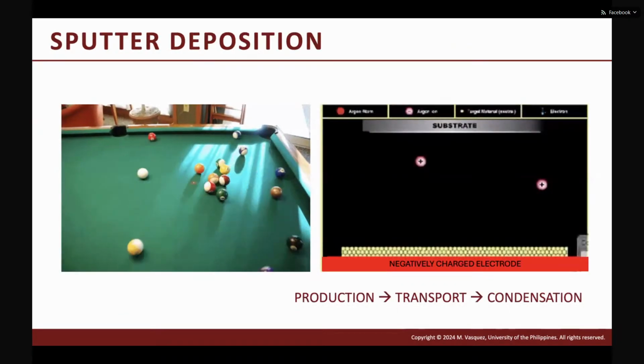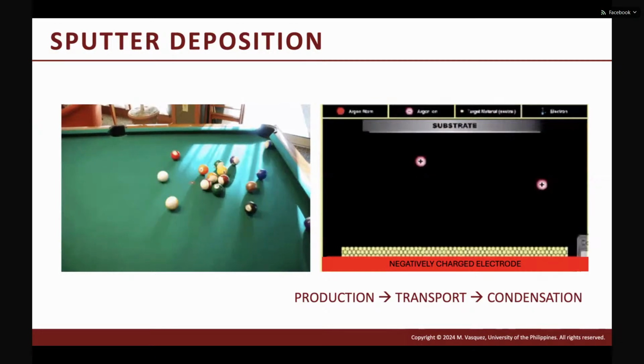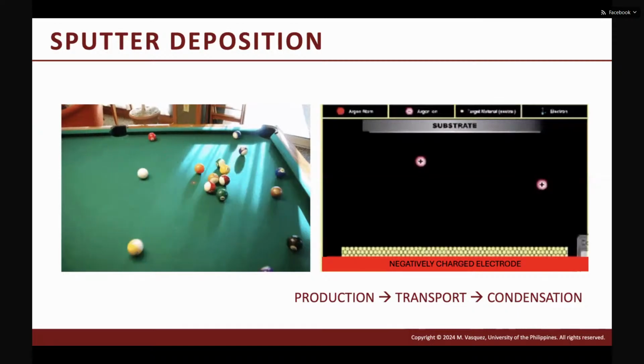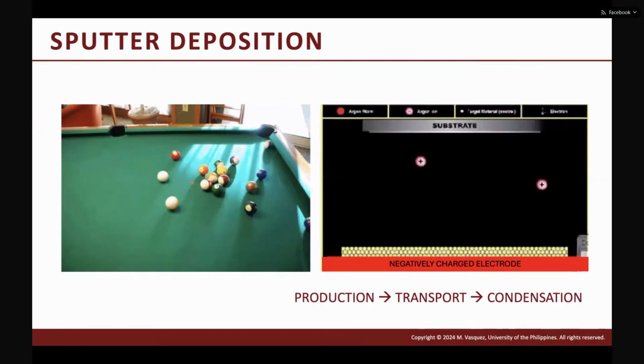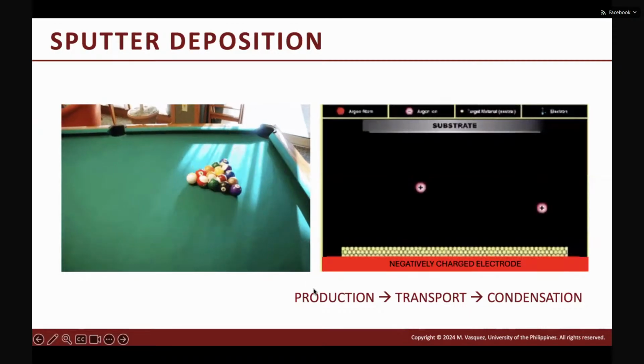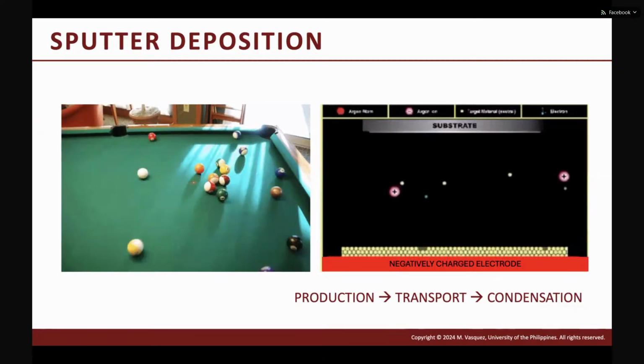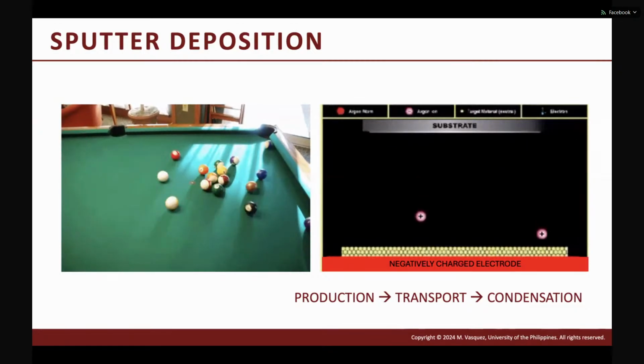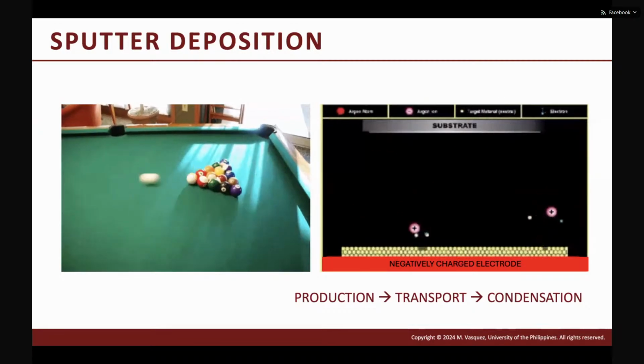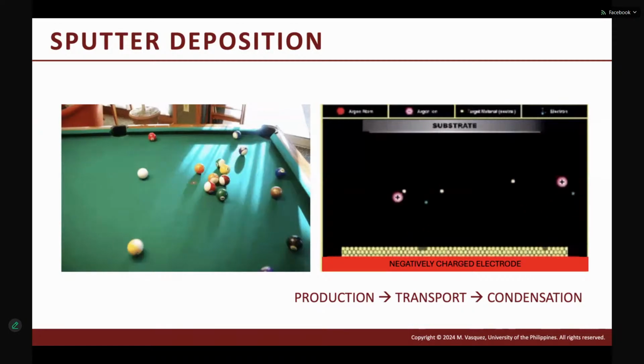So one of the major processes used in coating or growing thin films is sputter deposition. If you can imagine playing billiards, once the cue ball hits the billiard balls, they will just scatter. So the same principle is used in sputtering. So you have, let's say, an atom accelerated to the surface of a target, and depending on the energy, if the energy is high enough, then it is able to remove particles from the surface. So you have here the sputtering process.